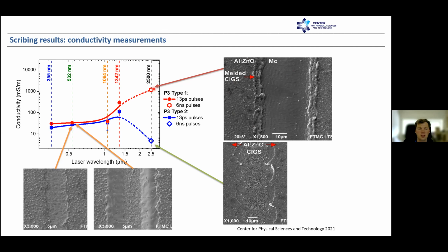That means we remelted the CIGS and induced some structural changes, and we have really induced parallel resistances, and this is really bad for the cell operation. But if we see for the P3 type 2, where we only gently remove the top contact, we see that the parallel resistance is actually very high. So selecting the proper wavelength for such multi-layer stack structuring is really important, and it's even more important than selecting shorter laser pulses.